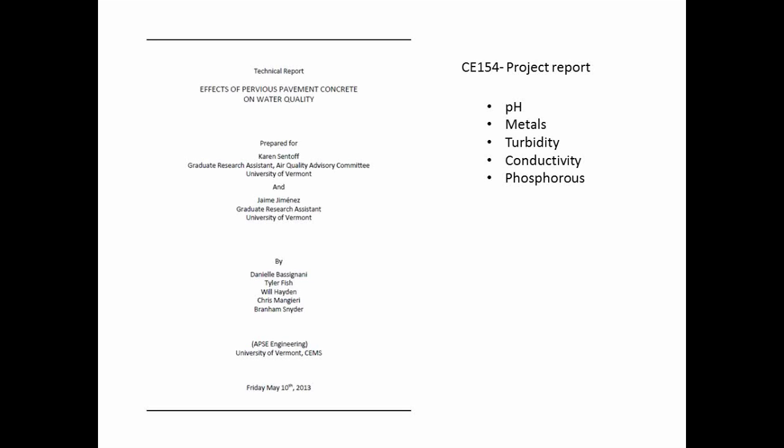I don't know offhand. Okay, so one of the big issues, and it's studied elsewhere, is the construction practice in the field and how much curing the actual concrete in the field gets. So in the lab, we make them in small cylinders, place them in a controlled fog environment, and they're really getting the treatment, fully cured. In the field, they'll lay it down, cover it with a tarp for 7 days, pull the tarp off, and let people drive on it, and salt it in the first year. So those sorts of differences are what some people are trying to quantify and what the end of our current freeze-thaw study is going to work on.